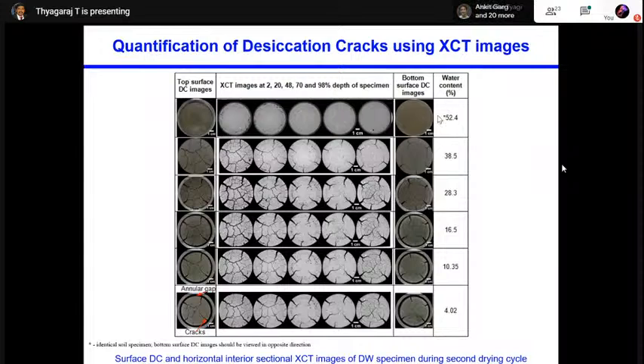After the first swelling, the water content was 52%. But when we dried it, the water content gradually decreased, and you can see this in these XCT images and digital camera images. There were no cracks here, and gradually the cracks increased.